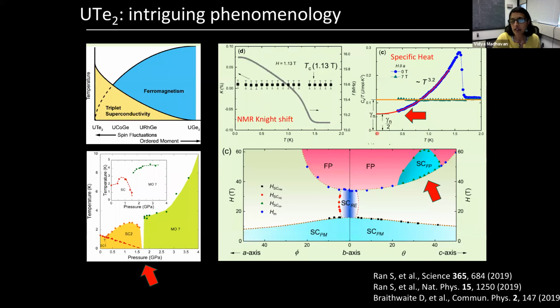If you're asking about this residual specific heat, this is not normal. You expect this, if in a superconducting phase, if all the electrons are paired, then this should go to 0. Now, sometimes I know that in some materials, initially for strontium ruthenate, for example, I think we did see sort of a residual specific heat signature. But that was much smaller. Also, one thing to realize here is this number is half the normal value. So this is not something that you would normally see in a superconductor.